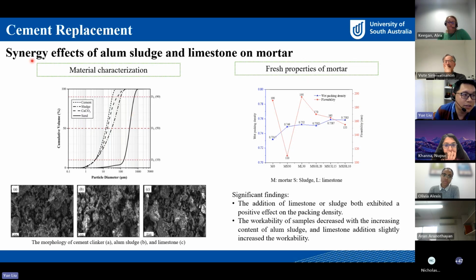That's why I conducted a study on the synergistic effect of alum sludge and limestone on mortar. Some interesting findings: when we added either limestone or sludge, it showed a positive effect on packing density. That's because the inclusion of limestone and sludge, with different particle size distributions, widens the spread of binder particle sizes, resulting in a greater packing density. For workability, because sludge has a very porous structure and absorbs a lot of water, it definitely decreases the workability of concrete. But limestone addition actually slightly increased the workability.